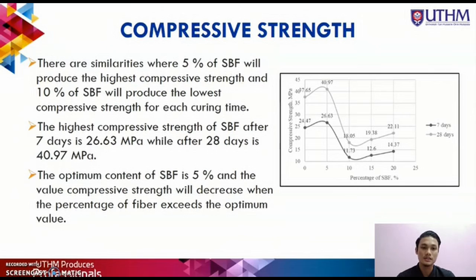It was observed that this comparison found similarities between 7 days and 28 days after curing, where 5% of SBF will produce the highest compressive strength and 10% of SBF will produce the lowest compressive strength. So, the value of compressive strength will decrease when the percentage of fiber exceeds the optimum value. That's all from me. Thank you.